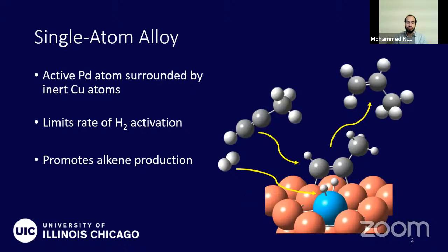So current catalytic techniques often use palladium or platinum-based metals, and those are active for hydrogenation because there's a low energy barrier in hydrogen activation. They split the hydrogen molecule to atomic hydrogen, which migrates across the surface and reacts with the adsorbed hydrocarbon. But the problem with those platinum and palladium type metals is they're very active, and you can hydrogenate all the way to the alkane, to the fully saturated product, which is undesirable. On the other hand, using transition metals like copper, they have a high activation energy for hydrogen activation, and so typically polymerization is a thermodynamic pathway for hydrocarbon reactions.